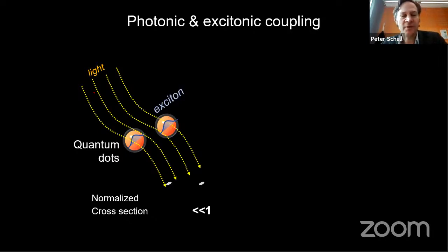So if you go from individual nanocrystals to these supercrystals, to these assembled ones, the individual ones have, let's say, two challenges or disadvantages. The first is that the interaction with light is small, because they're nanometer scale, they are in the Rayleigh scattering regime, so there's not much interaction. So their cross-section, normalized, so divided by the geometric cross-section, will be quite small, much smaller than 1. And also the charge carriers that you might create by impinging light are localized, they're not going to travel.